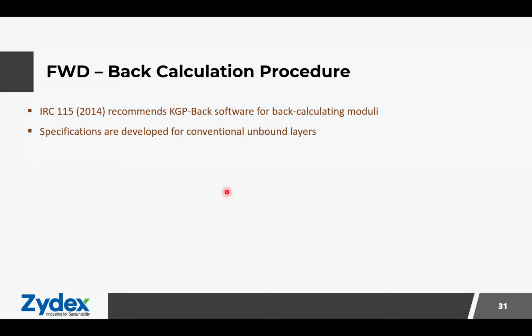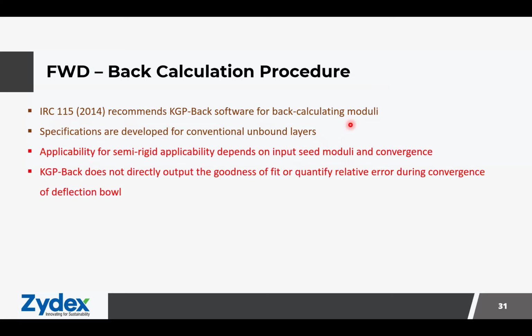Now, talking about the FWD back calculation procedure. We have the code IRC 115, which is practiced for the FWD back calculation procedure, but it is specifically developed for conventional unbound materials. It is based on a 3-layer system, that is the surface layer, the base layer, combined base and sub-base layer, and the subgrade layer. This code recommends KGP back software for back calculating moduli. Applicability to the semi-rigid pavement depends on the input seed moduli and the convergence that is taking place. But the issue is KGP back does not directly output the goodness of fit or quantify the relative error during convergence of a deflection bowl.